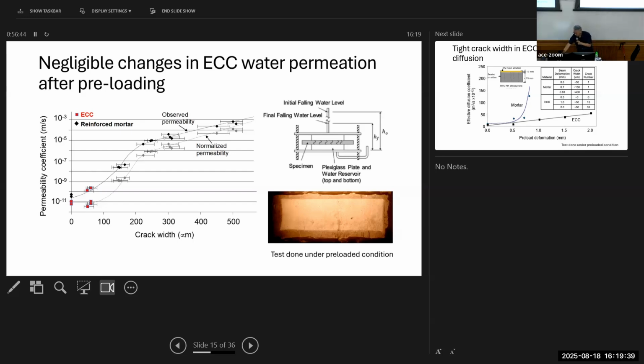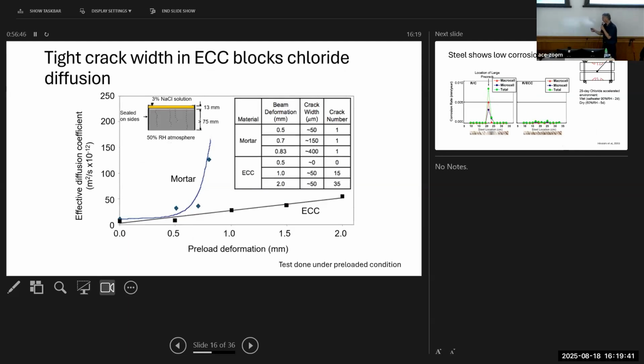Okay, so what about corrosion? So by ion diffusion, chloride ion diffusion, we did the same kind of experiment, preloading the two specimens under different imposed load deformation. And in the case of the mortar beam or slab, as we increase the beam deformation, you increase the crack width. That's what you expect, and there's only one crack there, but opening larger and larger. In the case of the ECC, even as we increase the deformation of the beam, we maintain very tight crack widths, with an increasing number of micro cracks.